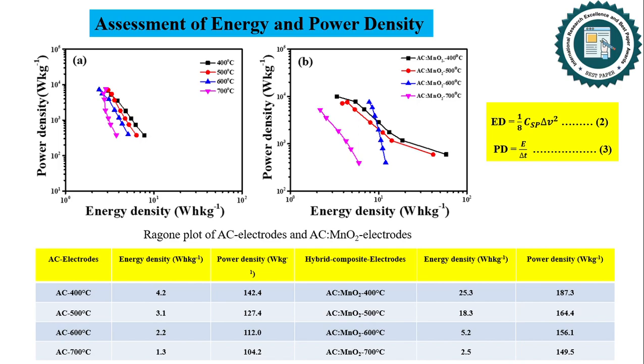Energy density and power density were evaluated to assess the performance of storage devices, with Ragone plots constructed based on galvanostatic charge-discharge measurements for AC and AC MnO2 electrodes, that is, activated carbon electrodes and hybrid composite electrodes. Equations incorporating specific capacitance, potential window, and discharge time were used for energy density and power density calculations, which are shown over here. Key findings revealed that activated AC 400 degrees centigrade exhibited the highest energy density of 4.2